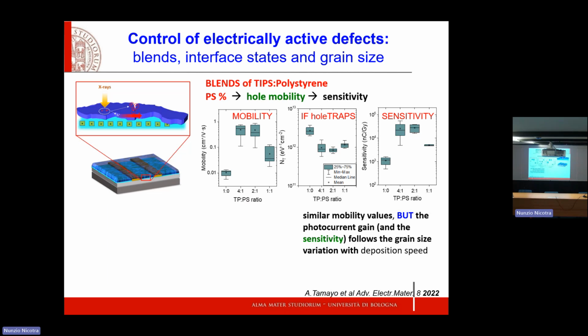So putting it together, this is another material, TIPS pentacene, blended with polystyrene. And we could definitely see that if we change the polystyrene and TIPS ratio, we can control the mobility, the mobility measured by this transistor, which has a maximum for a certain TIPS polystyrene ratio, and that is exactly going in the opposite direction of the density of interface majority carrier traps.